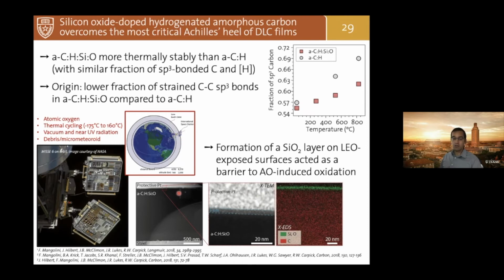What we could prove upon retrieval of the sample on Earth is that this material actually has a self-healing, self-protecting behavior, meaning that the addition of silicon and oxygen prevents the material from being completely burned away. If you take the same kind of material without silicon and oxygen in space, it is quickly gone in a few seconds because atomic oxygen basically burns away the carbon in these DLC coatings. If you introduce silicon and oxygen, and these were really nice images taken by Tom Scharf at UNT, you have the formation of this 5 nanometer silica-rich layer, which acts as an oxygen diffusion barrier and prevents the carbon underneath from reacting with atomic oxygen and being completely burned away as carbon dioxide, basically.